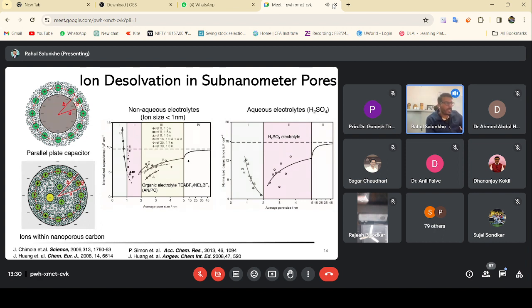Whereas if our material is a porous material, with a micropore structure available, then the ions go inside the material. So our material is negatively charged and the ions get inside the material. A large number of interactions are possible because the ions are inside as well as outside, and thus more ions can interact with the pore structure as well as the outer surface, and because of that the charge storage is more effective.